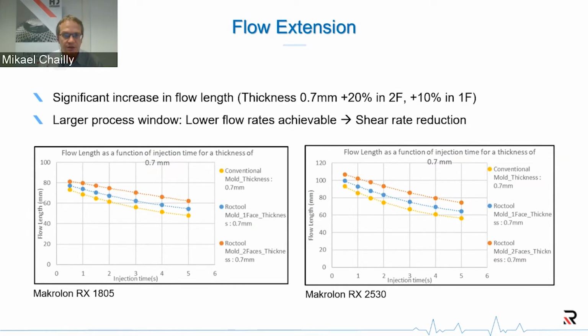or we could also reduce the filling rate by increasing the injection time, and this would have a dramatic effect on thin parts, especially for the shear rate generated during filling. So Roctool can help you do that. Now, if we go to the next configuration.